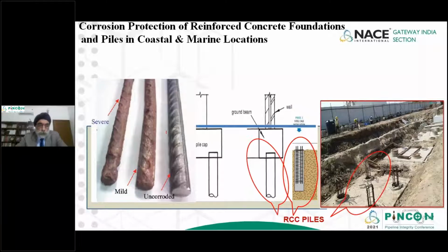corrosion. And then what happens, if you see on the left-hand side, you can see extensive pitting to severe pitting on the rebars. So the steel rebars start to lose their strength, and that, if it goes unchecked, can lead to a possible collapse of the concrete structure, leading to failure of a concrete structure. And all of you would have heard in the past that in coastal areas, steel reinforced bridges collapse. The reason why they collapse is primarily due to corrosion of the rebars. The concrete structure does not have strength to hold itself and it collapses.